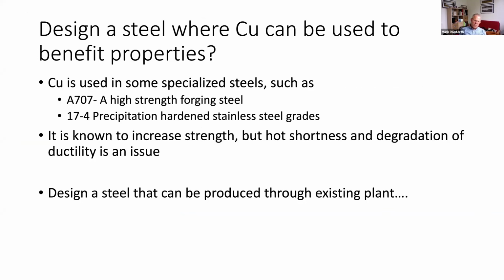And so we looked at this, and of course there are steel grades that are used which have higher copper already. So there's A707, which is a forging steel used, for example, in tension legs and oil platforms, which is a very high strength copper bearing steel. And then another example is 17-4 precipitation hardened stainless steel grades, where again there's 3 or 4% copper in there. But these are really very specialized steels and not for wider use.